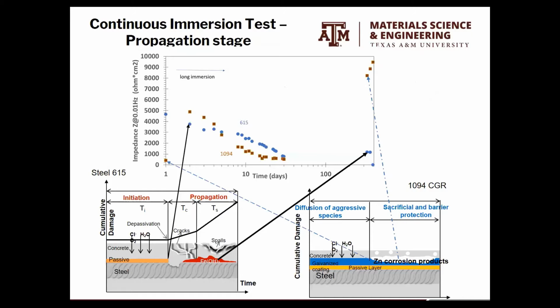So you see on the bottom part the rebar that has the typical initiation and propagation. And remember that we mentioned that the first set of experiments were simulating the activation, which is the propagation. We started from this point, which means that we skip the diffusing process. All the components that go to the concrete, penetrate and diffuse in the concrete, we skip that process, and we are in this stage in the steel, all right, which is the propagation.